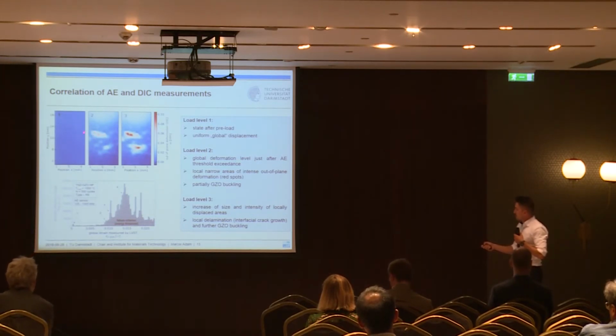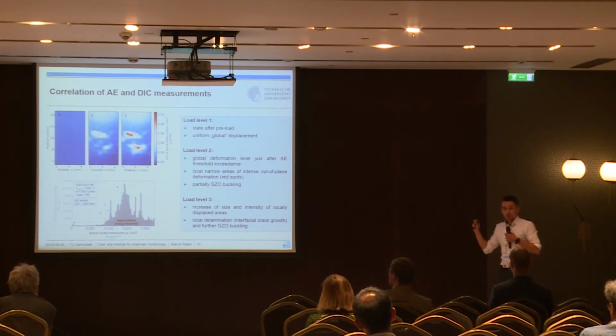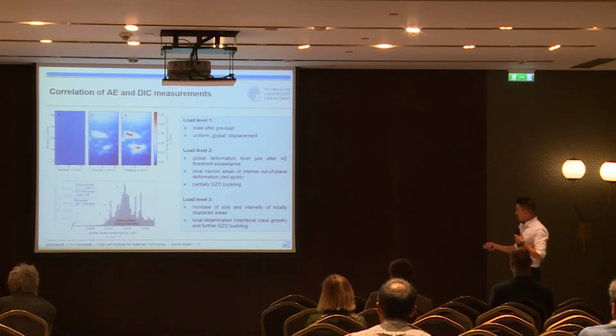And these spots belong to a partial buckling of our gadolinium zirconate layer. So the YSZ layer is intact, but only the gadolinium zirconate layer is going to fail. And with a further increase in the load, these red spots are going to increase in size and intensity, and the gadolinium zirconate buckling would be much more pronounced.